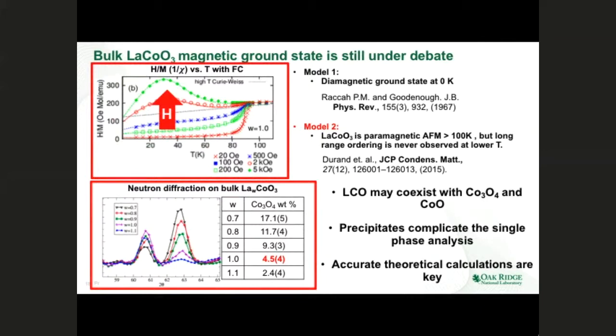But neither of these works has observed long-range magnetism at lower temperatures. So it is puzzling: since no long-range magnetism is observed, model 1 relies on a diamagnetic ground state, but model 2 suggests that there are still local moments on the cobalt atoms, but they are not ordered. Recent work using neutron diffraction spectra suggests that there is still nearly 4 to 5% Co3O4, or maybe some minor percentage of cobalt monoxide, coexisting in the sample. We know that Co3O4 is already a antiferromagnet at lower temperatures, near 0 Kelvin.